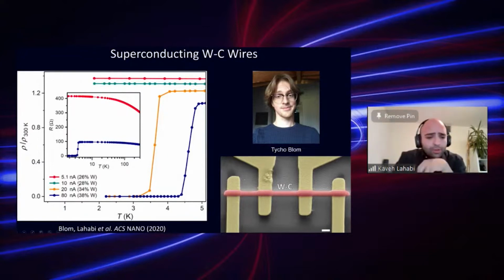One thing you should also notice is that by increasing the beam current, we also see an increase in the tungsten concentration in the deposited material. So that also is a signature of what we did differently, maybe. So the bottom line is that we managed to boost the temperature to 5 Kelvin or 4.5 Kelvin.